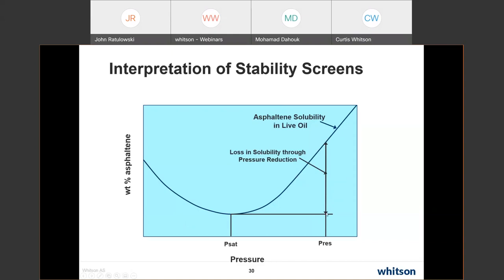So how much I lose is related to that compressibility. Lighter fluids will have more compressibility and they will lose more stability as I decrease pressure. Heavier fluids with less gas will not lose that much. The degree of undersaturation here, this pressure change from PSAT to PRES, also impacts this. So if I were at PSAT, then there would be no solubility loss through pressure reduction. So I won't have pressure-induced deposition, period, in the system. It just can't happen, no matter what my oil looks like. If I have a large delta P or undersaturation, then I'll get quite a bit of loss in stability, particularly if the system is very compressible.